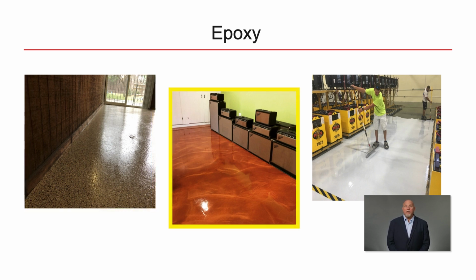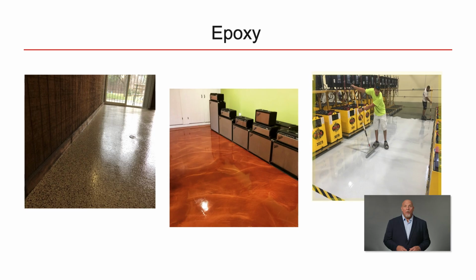The middle photo is a metallic epoxy. This is a special multi-layered epoxy floor coating system that incorporates the use of metallic additive mixed into a clear epoxy coating to create exotic effects. To the right is a heavy-duty 100% solids Novolac epoxy. These coatings stand up to the harshest chemicals in extreme industrial environments. The highest level of protection against the most corrosive industrial chemicals, even 98% sulfuric acid.